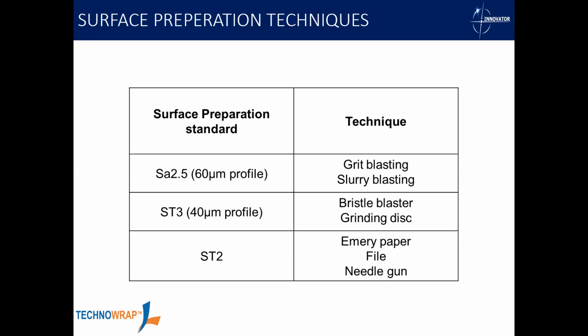So generally, we would look for a grit or sandblasted surface profile. This gives us the best cleanliness and the roughest, most irregular profile as well. So generally, we would work to an SA 2.5 standard with an average of a 60 micron angular profile. What we're seeing quite often, though, is the grit blasting teams are not available. So we offer bristle blasting. And we downgrade that slightly, even though if you've ever worked with a bristle blaster, you can get SA 2.5. But over a larger area, so the circumference of a pipe can be quite a large area, we derate that to an ST3 level of cleanliness and a slightly lower profile as well of 40 microns average.